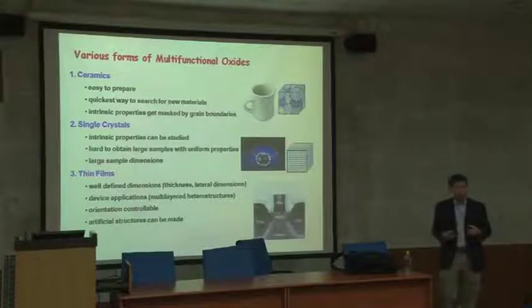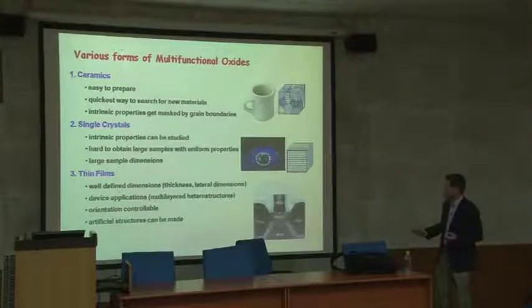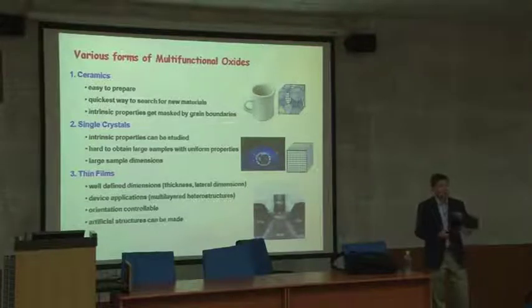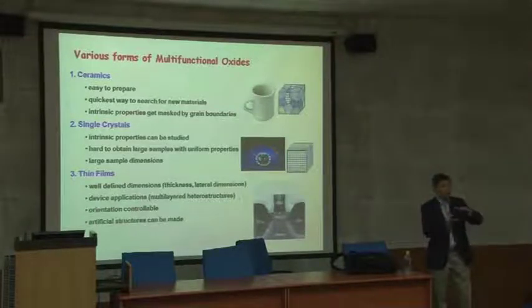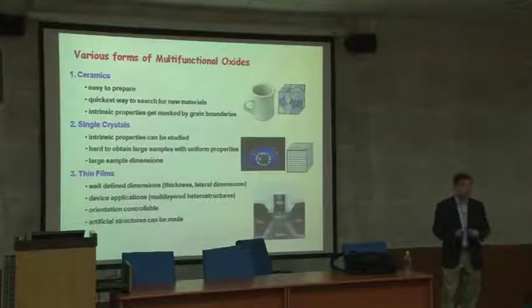And then most of the devices we use, similar to a semiconductor device, like gate dielectrics and the source and drains and silicon and then metals on top, you stack multiple layers for the electrode and active layers, so a multi-layer structure is needed. And stacking these with atomic precision, thin film is the only way you can do it. And with a bulk single crystal, you can machine it, but you cannot really go down less than 20 or 30 micron dimension, and you cannot go to nanometer scale, very hard to do that.